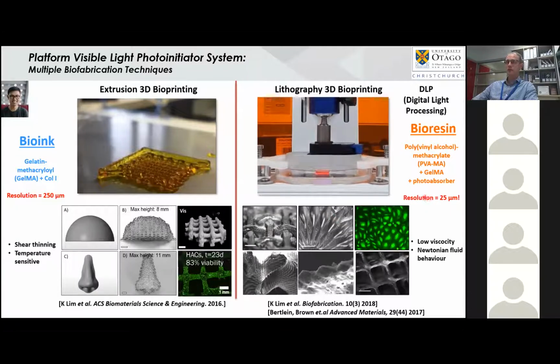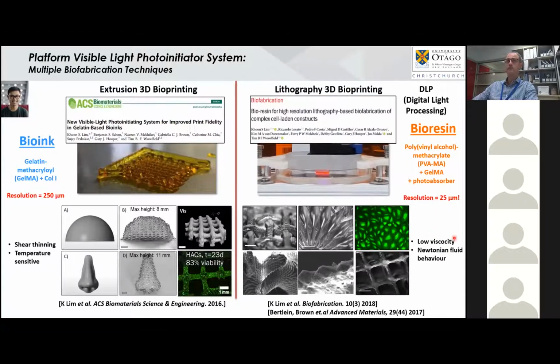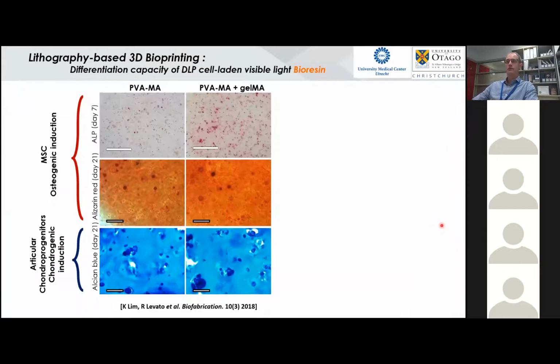And essentially the different pixel or voxel resolution we could achieve was down to about 25 microns. So again, this is another higher resolution layer by layer process. And with the addition of GelMA, we're able to incorporate cells within what we were then terming at this stage a bioresin, because it has quite unique features, which would dictate a difference from a standard bioink in terms of the types of low viscosity properties you would like, including a photoinitiator system. So if you want to find out more, there's a couple of the papers there.